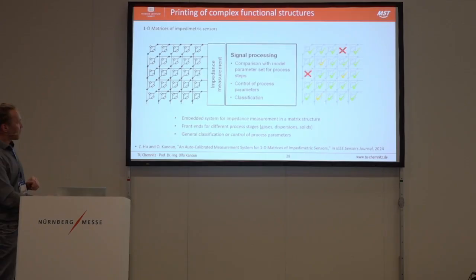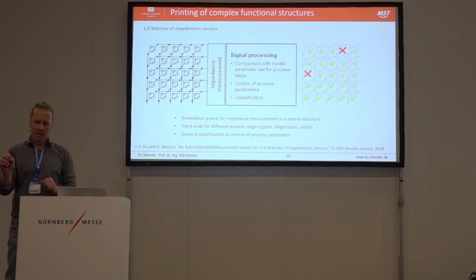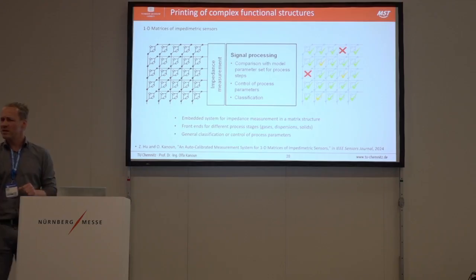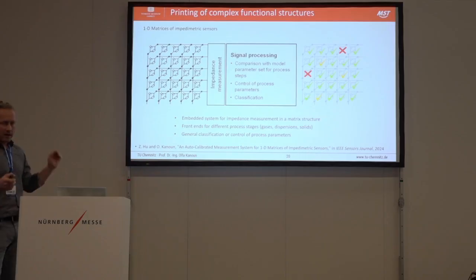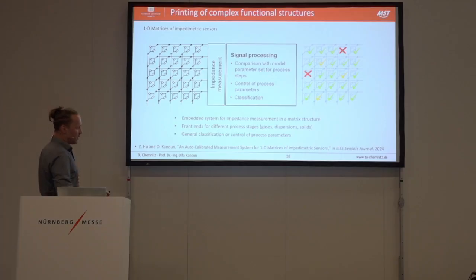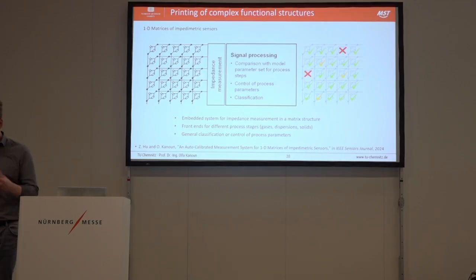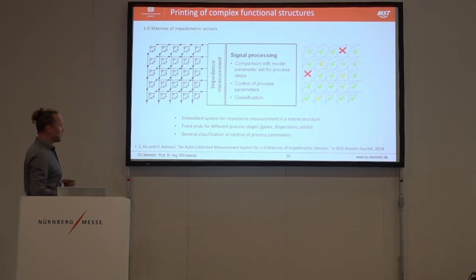We also have approaches for this. And we can generate from this matrix OK, OK, not OK. And maybe here the yellow one, maybe the process parameter should be adjusted, a little bit more heat, a little bit more oxygen, whatever, for the next production step to get it back. State of the art is that this complete matrix will be processed from beginning to end, and at the end you make an end-of-line test, and you find that you have a lot of waste. So this is, from our understanding, a huge contribution to improve the sustainability in printing processes.